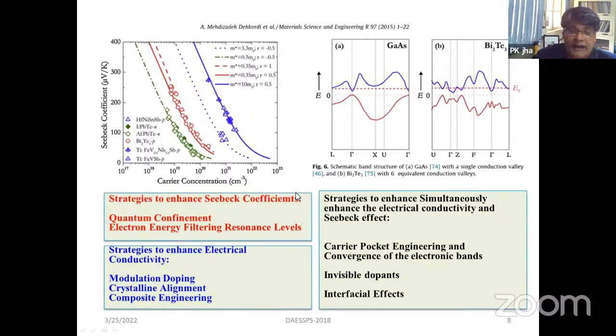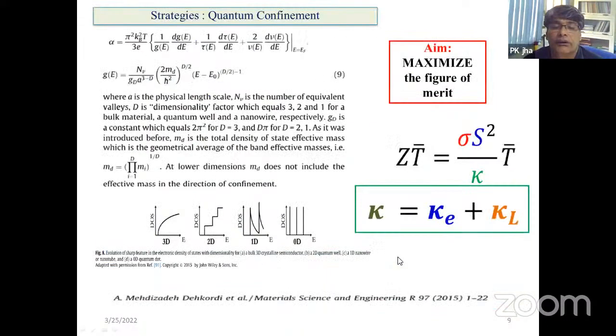So what should be the strategy, right? A strategy to enhance the Seebeck coefficient can be quantum confinement. That means making the materials at lower dimension, or in fact by nanostructuring. A strategy to enhance electrical conductivity can be modulation doping, crystalline alignment, composite engineering. A strategy to simultaneously enhance the electrical conductivity and Seebeck effect is carrier pocket engineering and convergence of electronic bands, resonant dopants, interfacial effects. So basically things finally come to the modification of the electronic band structure, which can be used to give you the best thermoelectric material in terms of the figure of merit.